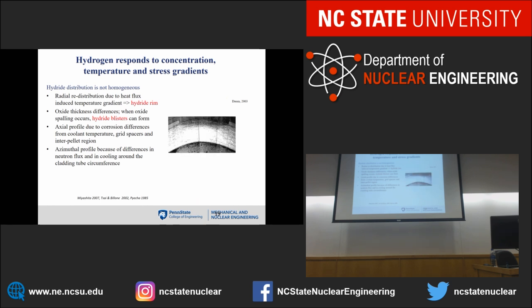And then we have azimuthal, when you have a differential along the azimuth. For example, the oxide spalling would be one, but I could also have, say, a corner rod where I have a greater heat transfer on this side than on that side. And I don't need very much. Something like a 10 degree difference will cause a big difference in the hydrogen content.